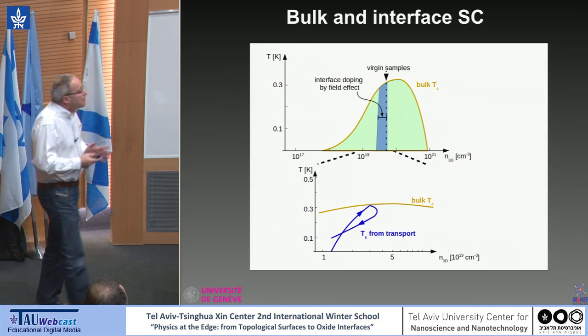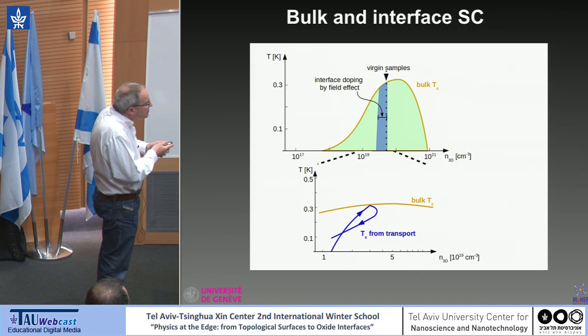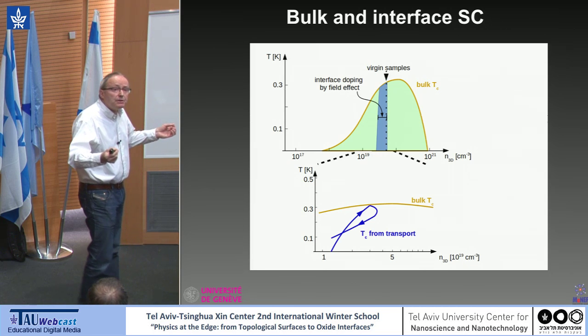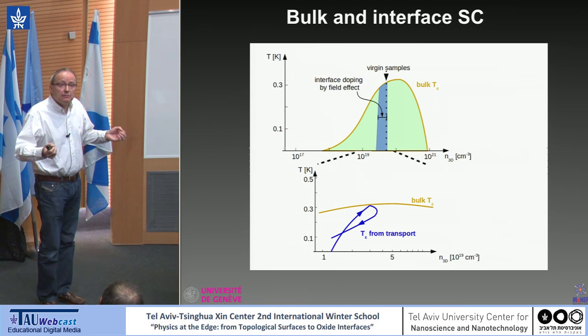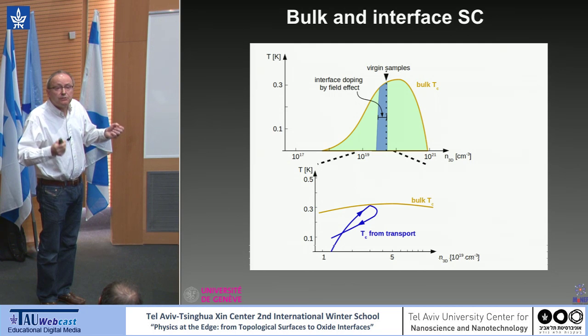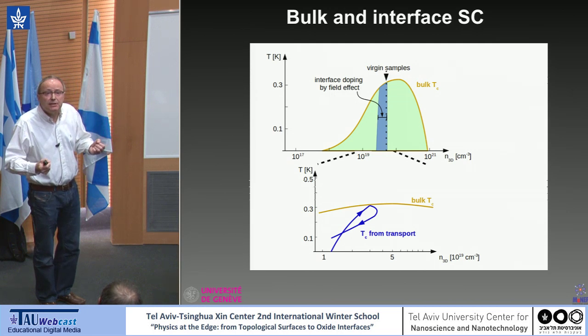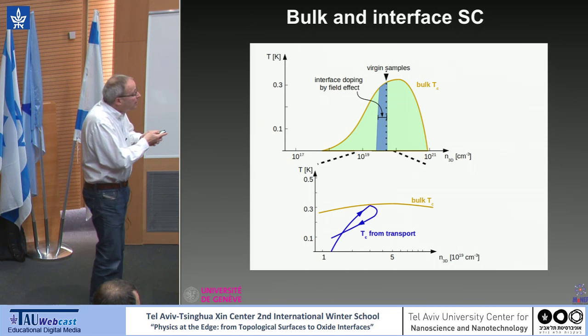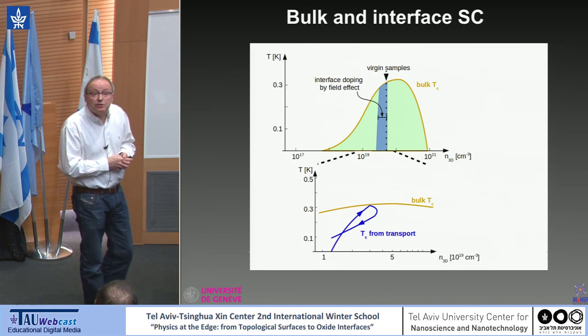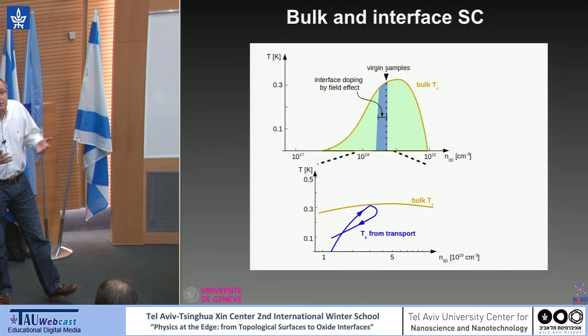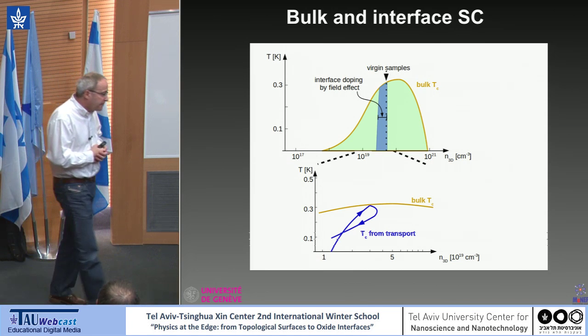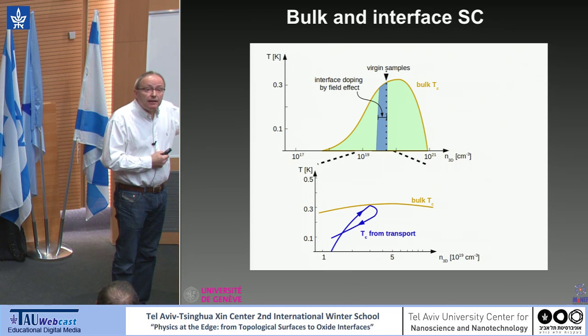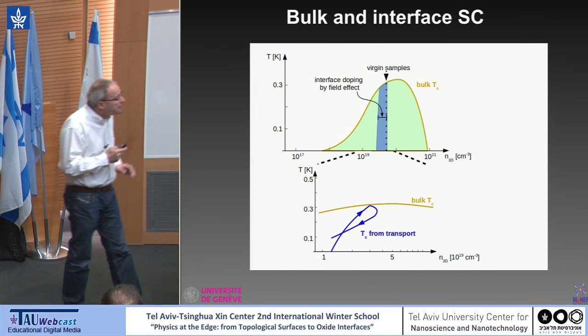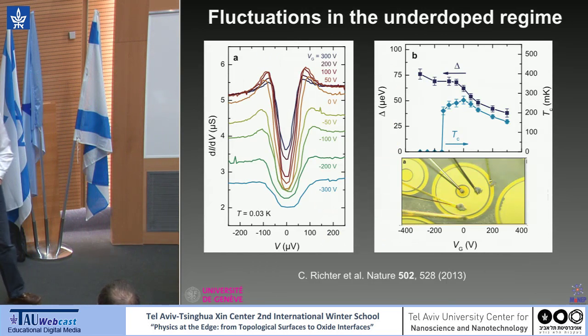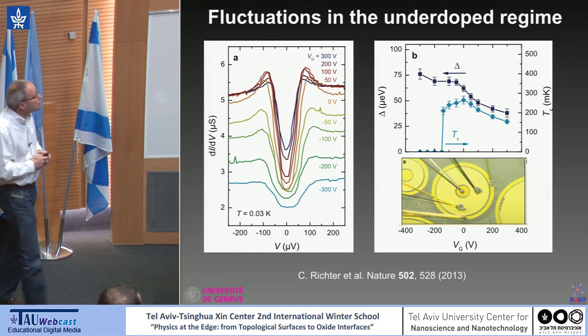I don't know. But what is interesting is that the properties of samples here for what we call underdoped and overdoped are completely different. If you look at the superconducting transitions, if you look at magneto-transport, it's completely different. And clearly the good parameter is not the 3D carrier density, which is the same, but maybe more the mobility or the conductance. To make things a little more complicated, let me mention recent work in Stuttgart in the group of Jochen Mannhart. This is the tunneling I was just mentioning.